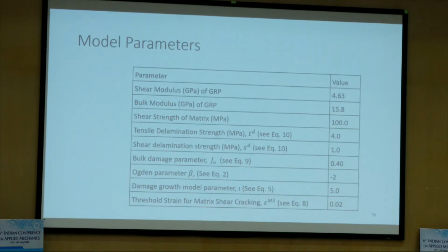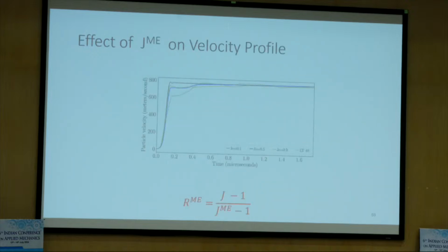We used DYNA3D, we got all the parameters, and then we did some sensitivity study. What is sensitivity study? You have parameters in your model. First you see how each parameter, when you change, how the particle velocity changes in your simulation. So here is an example. The one parameter, this is the damage initiation parameter under compression. And we said, this is important. When you put a material under compression in all directions, can you expand the volume?